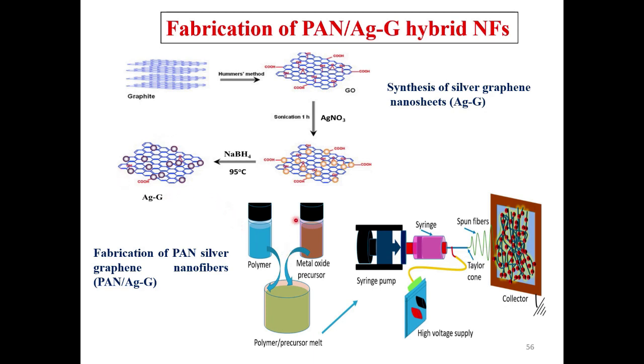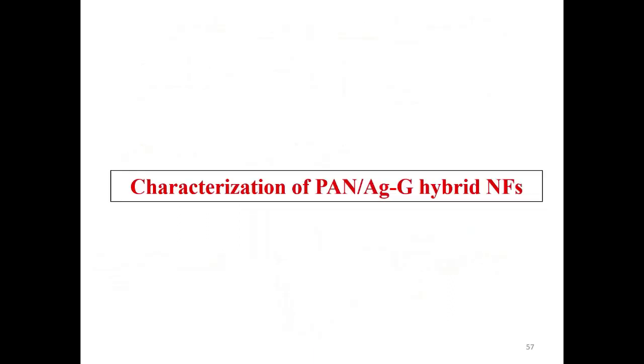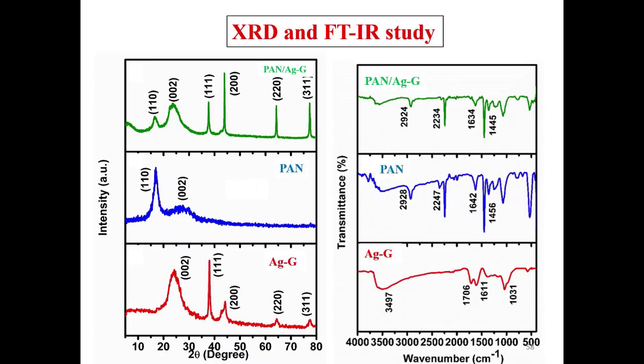The polymer PAN solution and the silver graphene sheet solution are combined together and put into the syringe, and we draw the fibers of polyacrylonitrile silver graphene nanofibers. Characterization, we have XRD and FTIR study. Presence of both the peaks in PAN-AgG, meaning PAN silver graphene sheet, is suggesting the formation of the nanofiber. We compare this with PAN and AgG, and it is observed that there is a formation of the nanofiber. The presence of the functional groups shows the formation of PAN-AgG nanofibers.